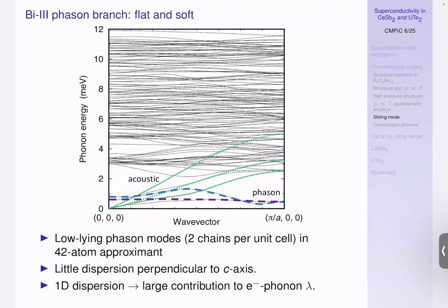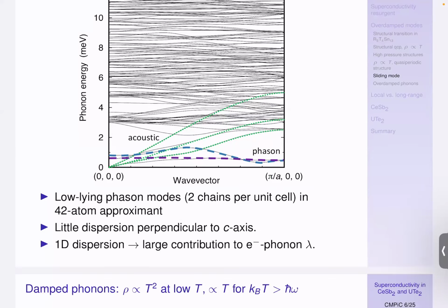Okay, so the idea here was Bartomeu Monserrat, at the time, he did phonon calculations using approximants, because you can't do it for the full incommensurate structure that would have infinitely many atoms per unit cell. So here he has 42 atoms per unit cell, so you have lots and lots of optical modes. And what you find is that, in fact, two come down in frequency and become soft. So this is even now for a commensurate, because it's an approximate structure. So it has a commensurate structure, but a large unit cell. And so you can convince yourself then by calculating the lambda for electron-phonon coupling for such a phonon spectrum that it is actually significantly enhanced by these low-lying optical modes.